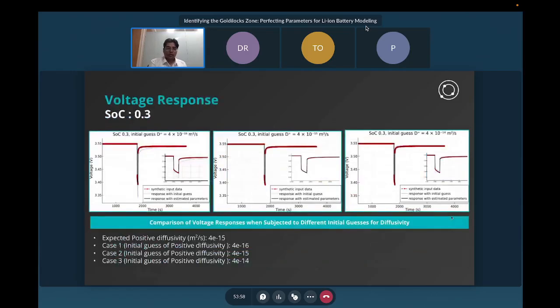Now, with this, we started with different initial guesses for the diffusivity, and here I have changed them by orders of magnitude, with 4e-15 being the reference value. For all of these, if you look at the pulses, when we optimize, each of these could capture the voltage profile during the pulses accurately. And that establishes that even if you are far off from the initial values, you will be able to capture the voltage profiles through the optimization process.